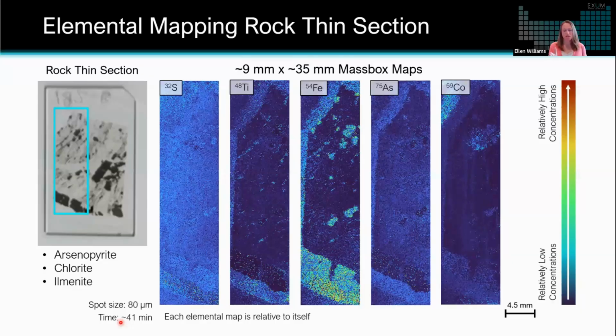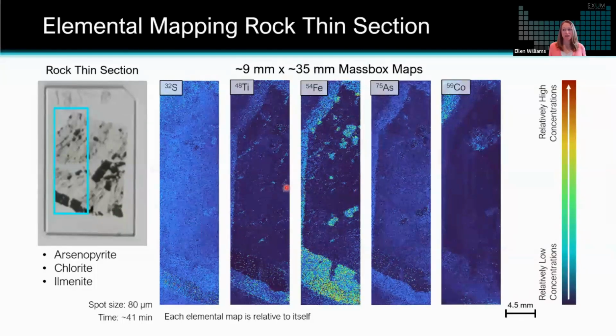And then when we look at these elemental maps, each one is on its own relative scale where we see these reds, these oranges, those are relatively high amounts of a given element. So for example, you can see on the iron map, there are distinct areas with relatively high iron. And then on the titanium map, we see areas where titanium is relatively high that correspond with other areas of the sample. So titanium being a major component of the ilmenite, and then iron giving us other mineralogic cues.